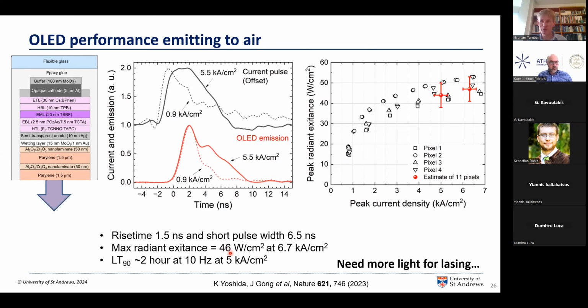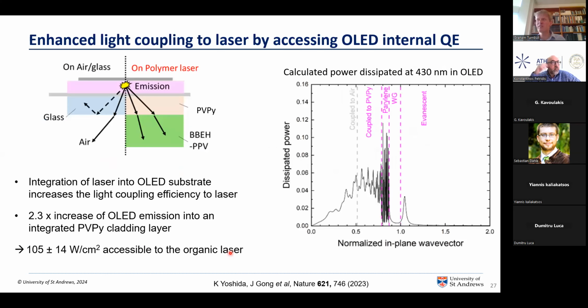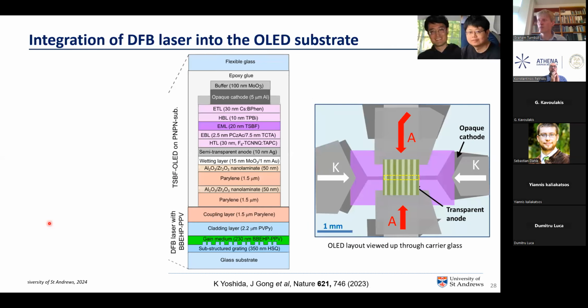So this is not the 100 watts per square centimeter we need, but we're getting part of the way there. And the way we get the whole way there to drive the laser above threshold is that we have to carefully and completely integrate the laser into the OLED substrate. By integrating the laser gain medium into the OLED substrate, we avoid some of the total internal reflection losses that you have in the glass, and we estimate through calculations that we can increase the radiance to the gain medium by a factor of about 2 to 2.5, which gets us enough to potentially go above threshold.